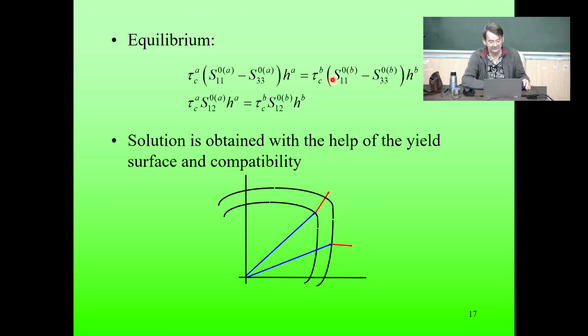And these are the stress states due to the texture here and due to the hardening of the material. So these equations are to be solved. What is unknown is HB. How HB is going to change during the strain. We have an initial state for the thickness, and it's going to be decreasing. So the HB over HA ratio will be decreasing. This is how deformation is localizing.